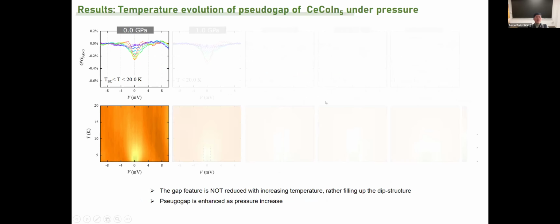Okay, so this is the color plot of the differential conductance at ambient pressure, where the temperature range is above TC to emphasize the new feature. As you can see, at ambient pressure this is a pseudogap-like feature, and the gap is pretty much filled.